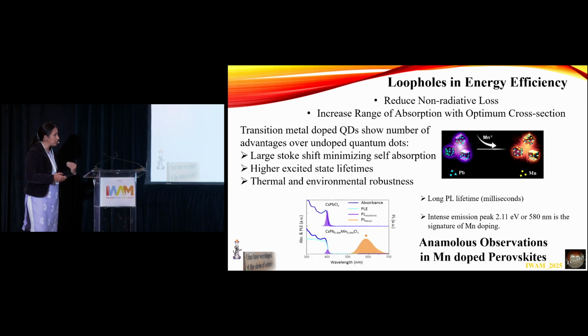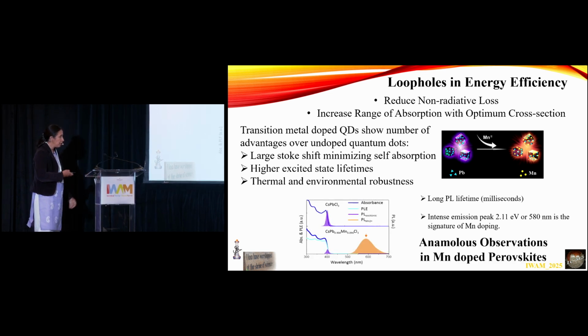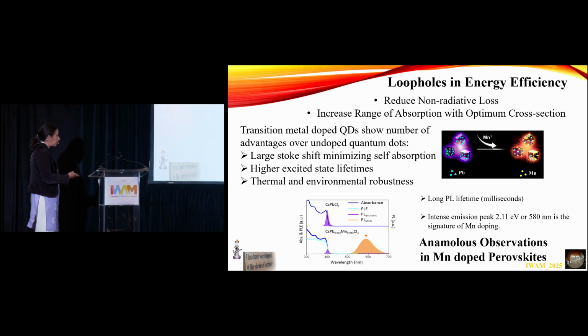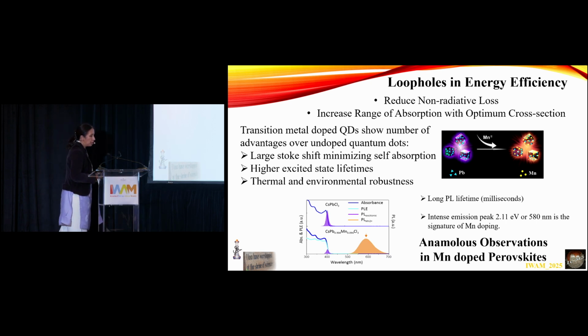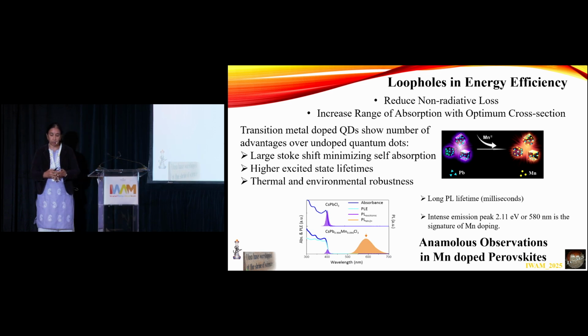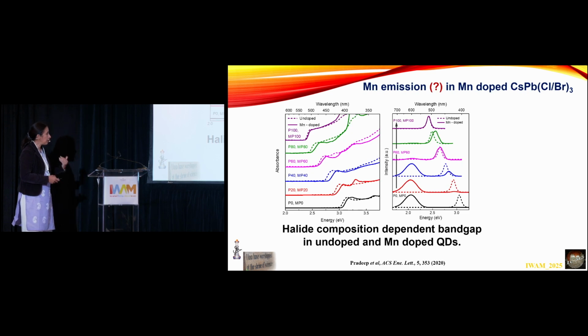When this was transferred onto the perovskite, it did give some very similar results in cesium lead chloride. But at the same time, there were a huge number of anomalous observations in manganese-doped perovskites, specifically in cesium lead bromide and similar systems. When I say anomalous effects, what do I mean?